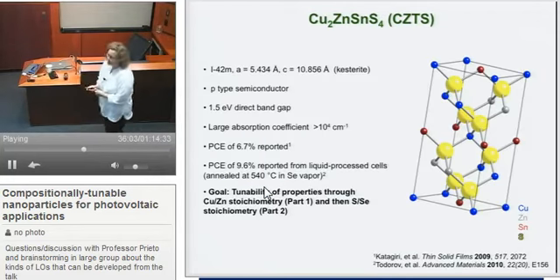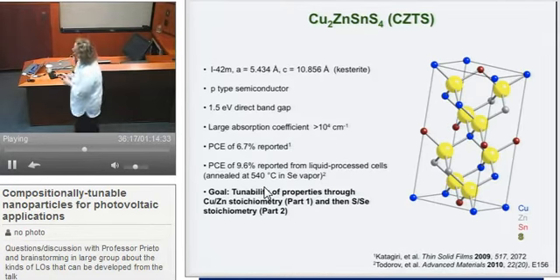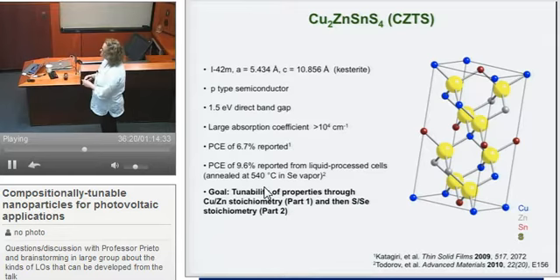So this is the structure on the right. I know a lot of you now have a primer on CrystalMaker. What's important about this structure is it's actually, in theory, pretty simple. I'm showing you copper in blue, zinc in gray, tin in red, and sulfur in yellow. And what's important here is really the ordering. So in this cartoon, which looks very idealized, you have 8 sites that are important. 2 coppers here and 2 zincs here, and then the crystallographically related sites down here, 2 coppers and 2 zincs. So I'm showing you one ordering. By the end of the talk, I hope I convince you that there is nothing in real life that's this simple. And so there's a lot we have still left to understand.